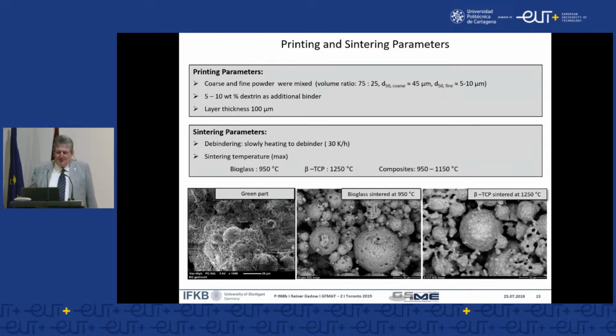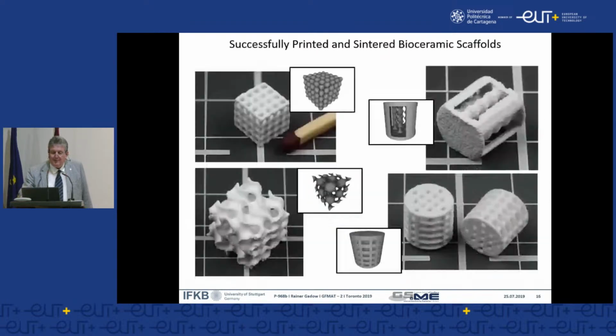Step by step we could increase the green density, and for sure step by step we could optimize the sintering and also the printing conditions, so that the desired geometry was obtained. So here you have a selection. For easy understanding and comparison, you see a matchstick, which has typically a dimension of 2 by 2 millimeters. In the case of these implants for rabbits, we remained in a sample diameter of less than half a centimeter, and the maximum length can be varied according to what is desired.